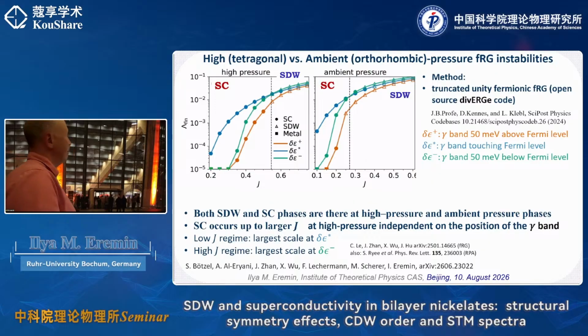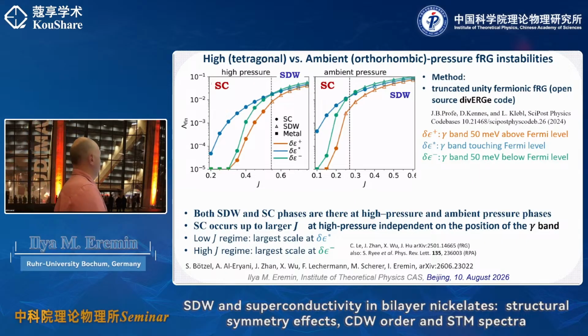And then what you notice is that at high pressure, indeed, the largest part of the phase space is taken by superconductivity, which is S plus minus superconductivity in this case. However, if you raise the J, it becomes also a spin density wave metal. The same, by the way, spin density wave as before. But if you do it at the ambient pressure, you still see that the overall phase space now is dominated by the spin density wave, but you still have superconductivity, still for reasonable values of the J.